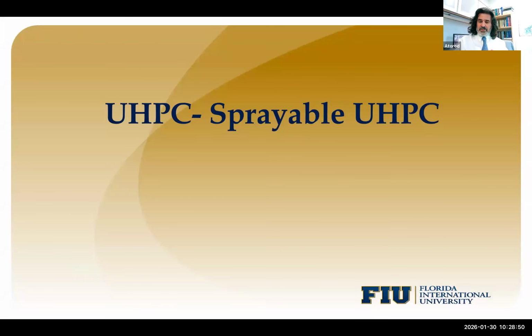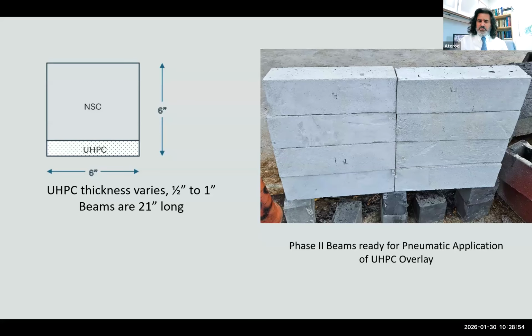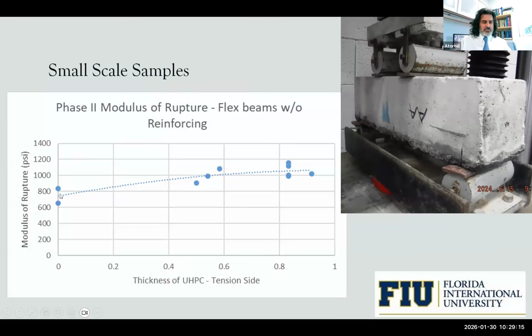Now, coming back to sprayable UHPC, we've done quite a bit of testing to understand the properties of structures that are sprayed with UHPC. We took some small beams, standard ASTM size, and cast in place or sprayed UHPC onto them, and then did the flexural test by putting the bottom in tension. You can see that the modulus of rupture, or tensile capacity, of the bottom side of the beam without any reinforcement goes from about 700 to 1200. This is just by casting a very thin layer, 1 inch or so, of UHPC, or spraying the UHPC. By the way, there is no difference between them. That can add quite a bit to the tensile capacity.